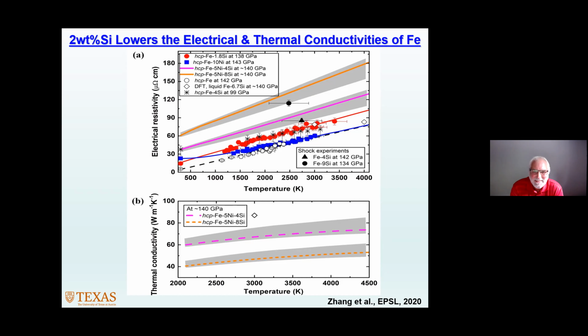Yeah, so we did not go into the melt, and the reason was really because once you go into the melt, the sample shape and thickness would change dramatically. So your resistance data would be pretty much useless. But even before that, we can approach the melting because of the recrystallization of iron alloys under high pressure, high temperature conditions, and that would also affect the values. You can have texturing in the sample that affects your resistance. So we typically limit ourselves below the recrystallization temperature.